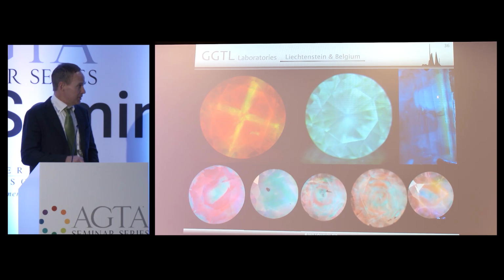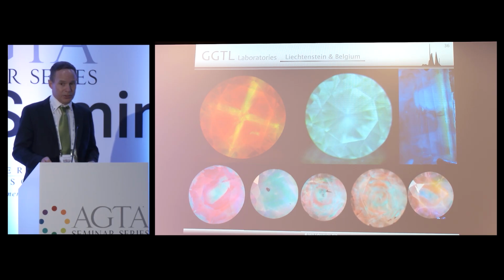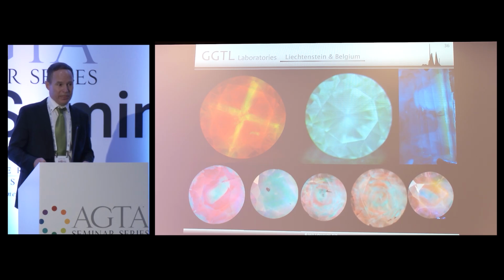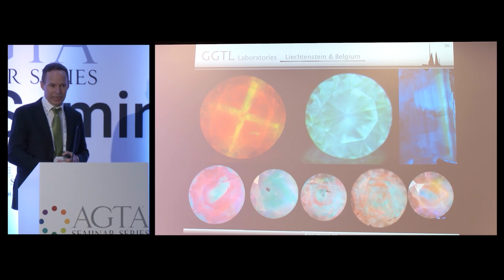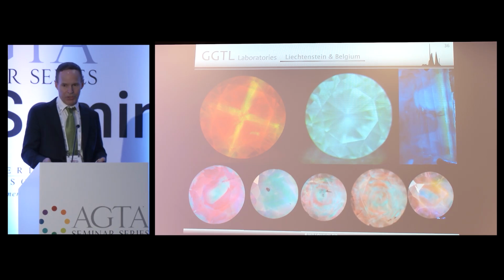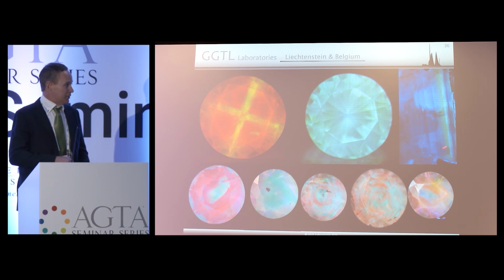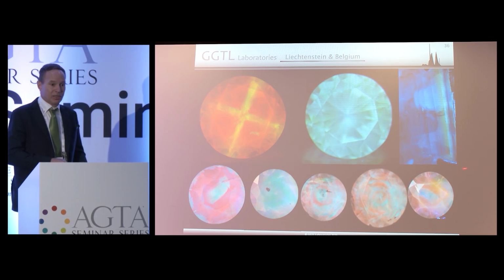But sometimes you do see surface-related fluorescence like this. That basically tells you how deep your irradiation went. Today, most material is electron irradiated. Electron irradiation, especially when you go at lower energies, doesn't penetrate very deep into your diamond. So you penetrate maybe a millimeter, millimeter and a half. And if the stone got some heat during the irradiation, you will have H3 center accumulated inside your color layer.